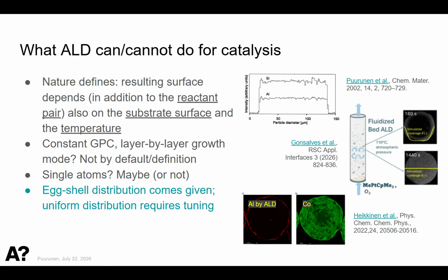And one thing that I do want to tell for anyone who is interested in ALD for catalysis is that when you work with porous materials, when you work with catalyst supports, ALD will necessarily start as a coating from the outside that then penetrates deeper inside. So you get an eggshell coating always in the beginning. Many people have, to my understanding, assumed that because it's ALD, you would have conformal coating right away, but that does not come automatically. That needs time and that needs a higher amount of exposure. So here are examples of a nice uniform distribution already from my doctoral thesis works in 2002, long ago. TMA ammonia process had been used and we got a nice constant aluminum to silicon ratio through the particle.